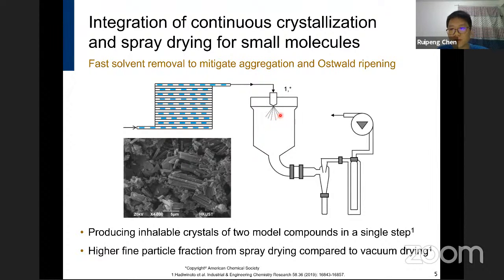Ostwald ripening, in brief, is a phenomenon where the coarse particles could grow at the expense of the fine particles redissolving. Aggregation and Ostwald ripening, these two phenomena, can affect the bioavailability and reduce the stability of the product samples. In this work, it was also shown that a high fine particle fraction from spray drying was obtained compared to the conventional vacuum drying method due to reduced agglomeration.